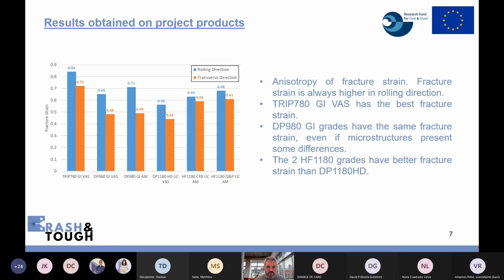So here what we can see is that first, all products have a big anisotropy of fracture. Generally, the fracture strain is always higher in rolling direction. We can also see that the best ductility is reached for the TRIP780 product. Secondly, we can see that the DP980 grades have the same ductility. It's more or less equivalent in both directions. And finally, regarding the HF grades, they have very satisfying ductility, a little bit higher than the DP-HD grade. So that's for the classification of the products in terms of local ductility.